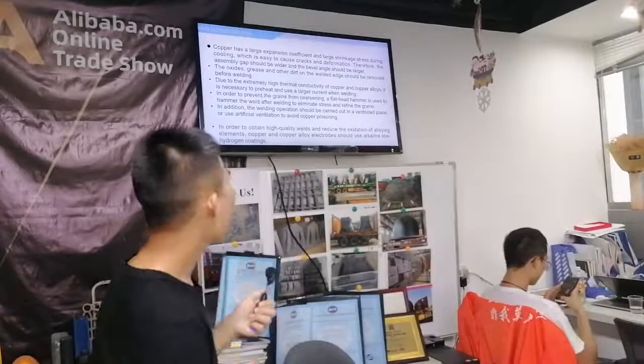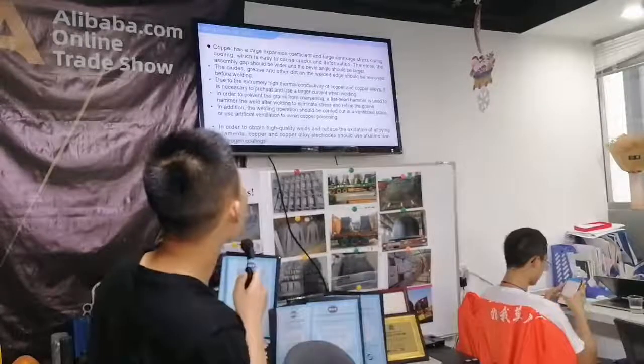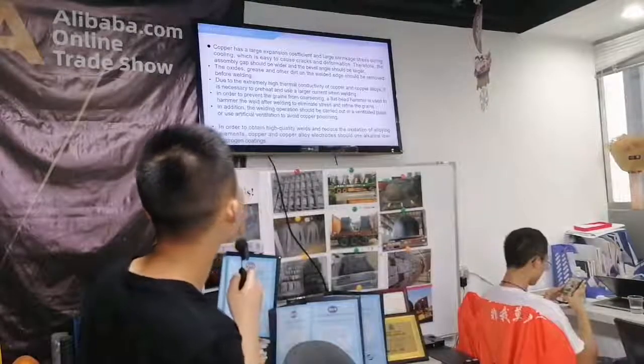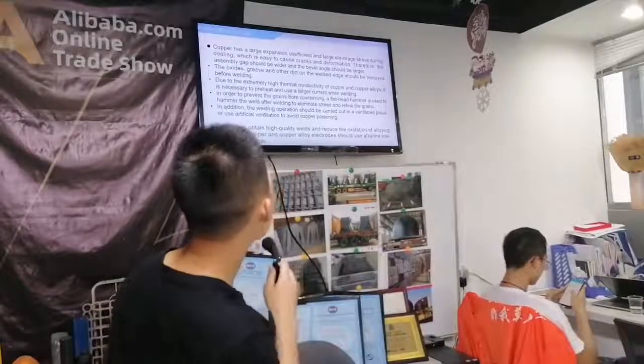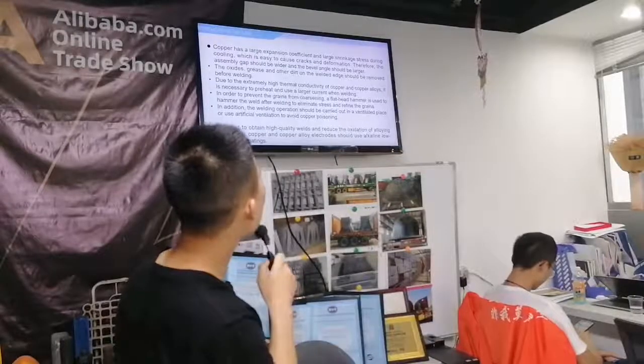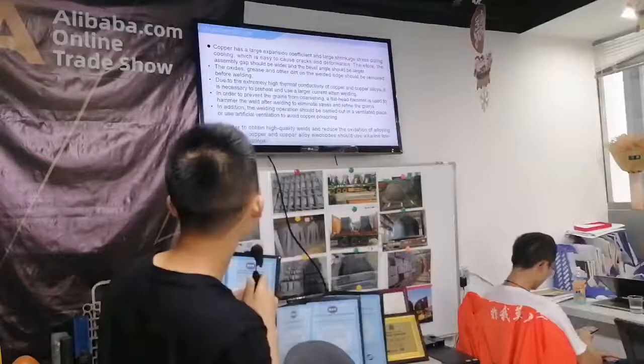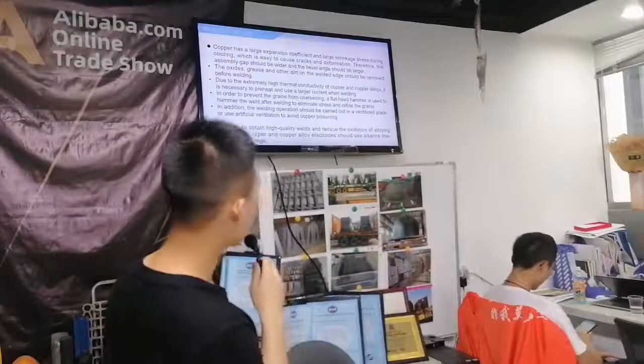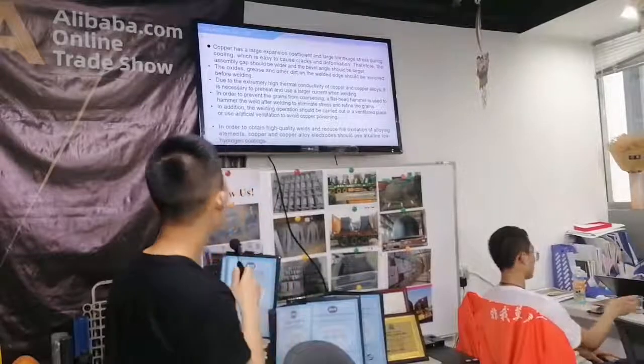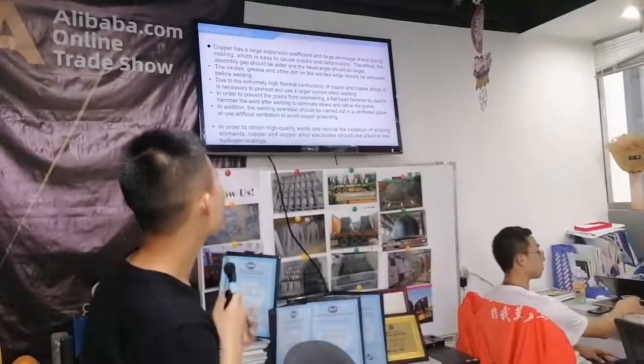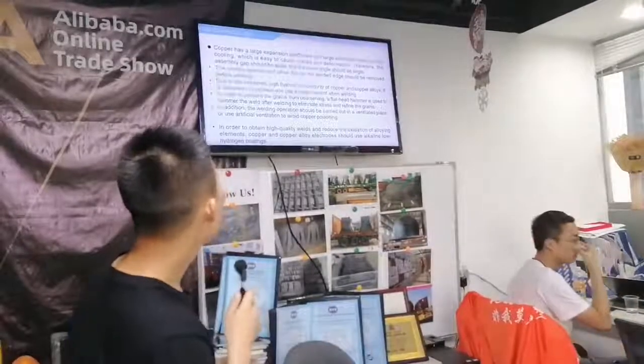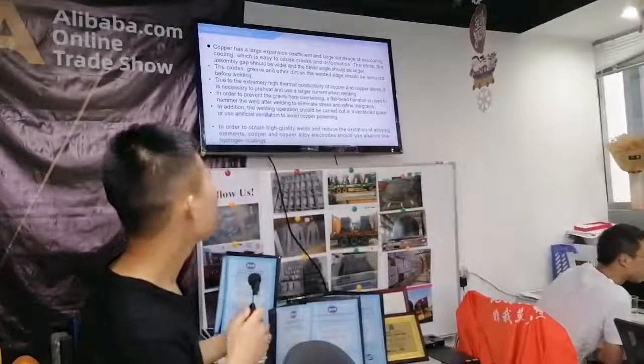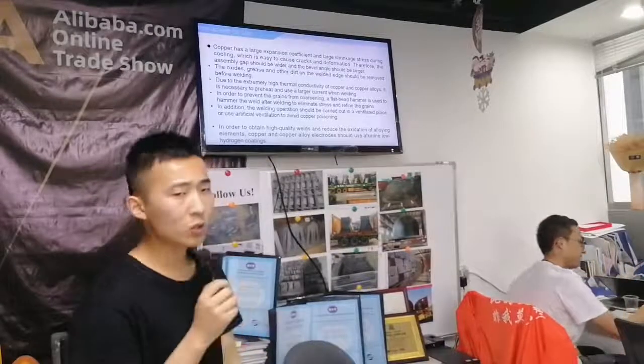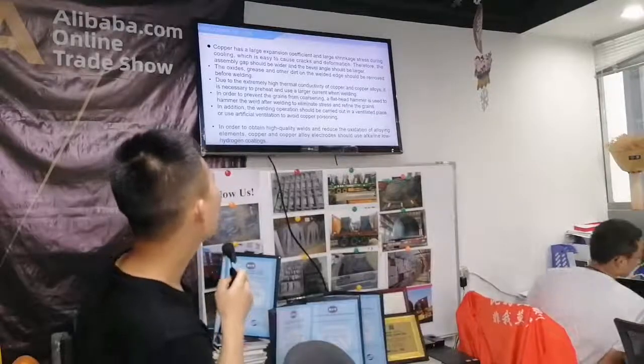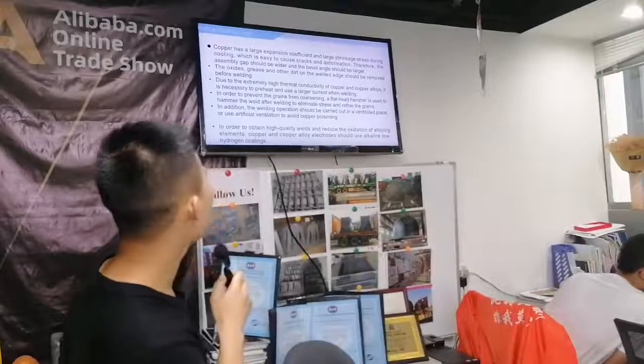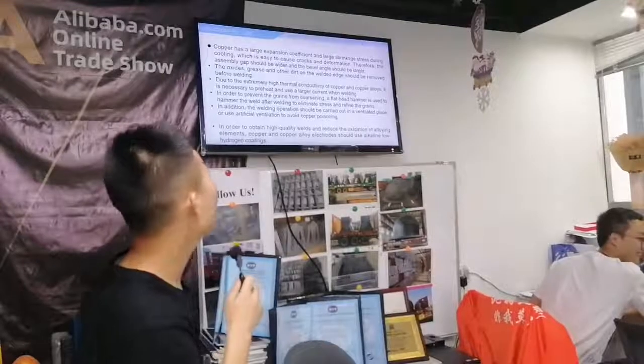Instructions for use. Copper has a large expansion coefficient and large shrinkage stress during cooling, which easily causes cracks and deformation. Therefore, the assembly gap should be wider and the bevel angle should be large. One, oxides, grease and other dirt on the welded edge should be removed before welding. Two, due to the extremely high thermal conductivity of copper and copper alloys, it is necessary to preheat and use a larger current when welding.